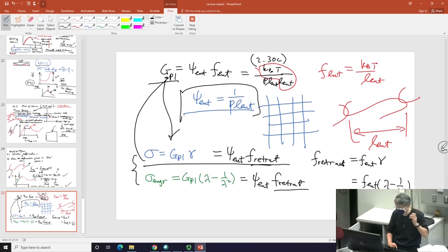This is, of course, the simple rubber elasticity kind of concept, very much still along the way that the tube model assumes, which is that the force is coming from intrachain. The interchain does what? It does the uncrossability. It does nothing else. The interchain produces uncrossability, produces the junctions. Okay, so this force is known. Now we just have to deal with the other force, the intermolecular gripping force.